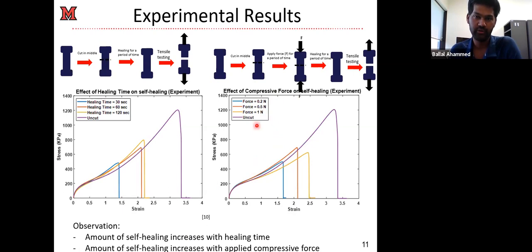So we found that when we applied more compressive forces, the material heals better in terms of its peak stress, and the strain values are also doing better when you apply the forces. So both of them have a positive effect.